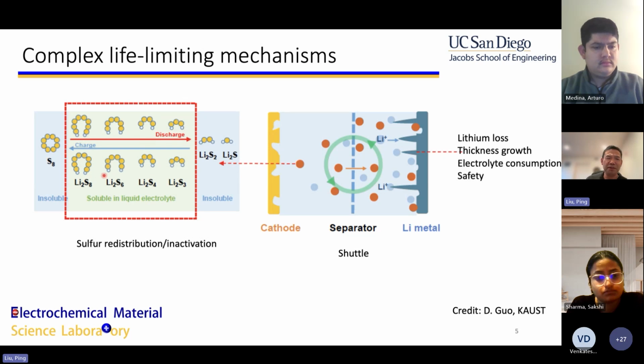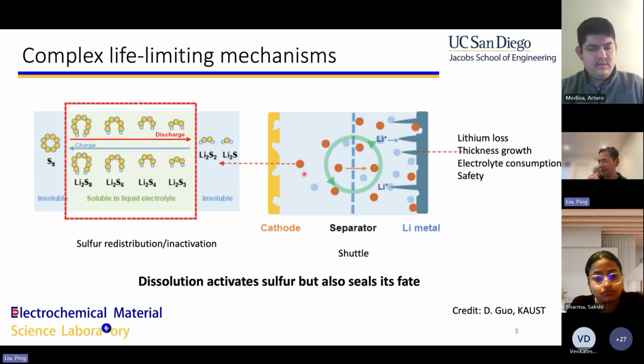Say we make a sulfur cell with lithium metal, and it just circulates between the anode and the cathode. It can do terrible things. But I want to remind you that it's not all terrible. The fact that sulfur is a perfect insulator, this dissolution mechanism actually activates it. That's the only reason the battery works for a few cycles at all. Otherwise, you wouldn't get anything out of a perfect insulator. So this dissolution mechanism makes sulfur work, and also kills it. It's two sides of the same coin.